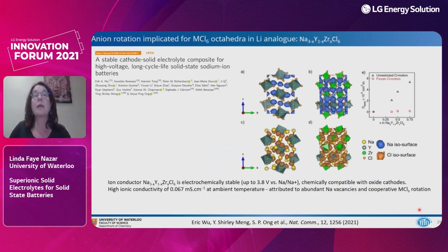So I might add that Shirley Meng's group has reported on, I guess we'd call it, a sodium analog to this phase. So it's the sodium version of the zirconium-substituted yttrium phase, where she's working together with Shyue Ping Ong, and they've seen the effects of anion rotation for the MCl6 octahedra in this material. And this is a paper published in Nature Communications this year. And this just shows the results of their AIMD calculations, where if they unrestrict the chlorine motion, you can see very high diffusivities. Where they freeze it, computationally, you can see quite low diffusivities.